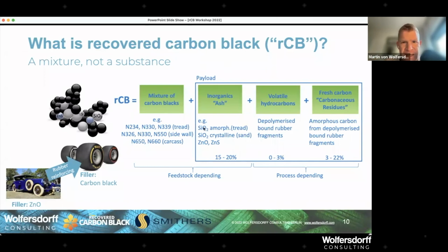And then, of course, the silica is a major part, certainly for Europe, the amorphous silica. It's the same as with the carbon, where we can have amorphous carbon and we can have crystalline or graphitic carbon. Silica is also in both modifications, and the precipitated silica is added as a high-performance filler for the tire treads to provide lower rolling resistance and higher grip. Unfortunately for the tire, the wear rate also goes up, so the longevity of the tire goes down if you use silica.